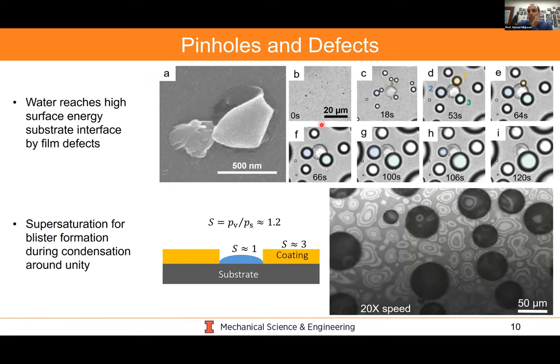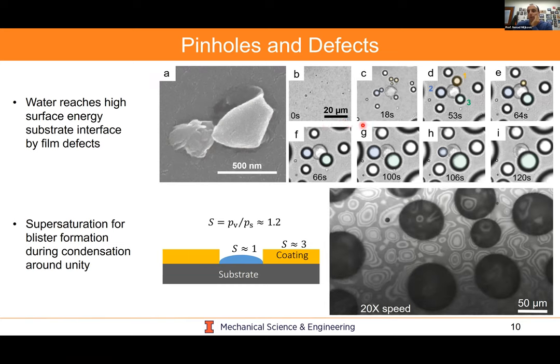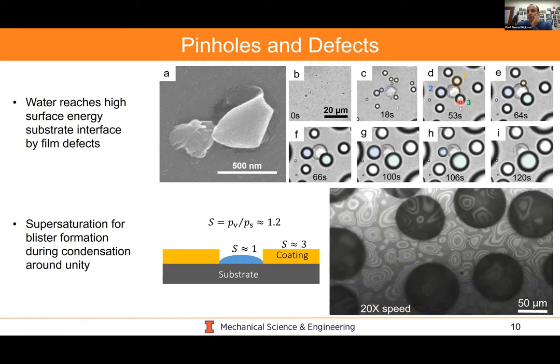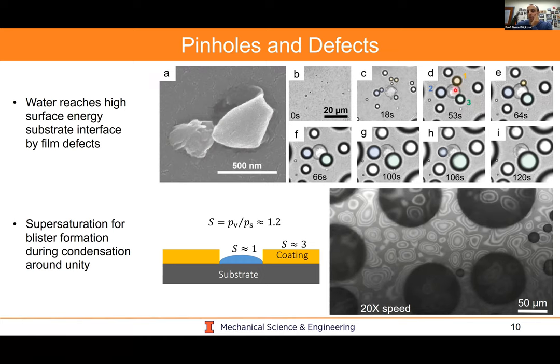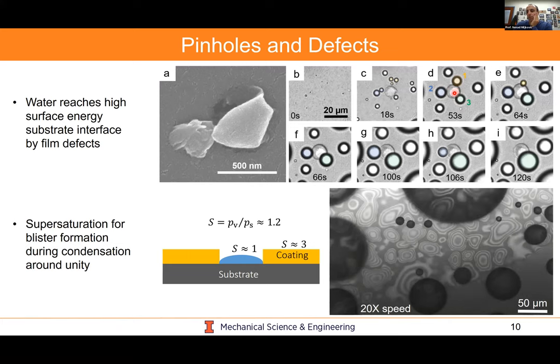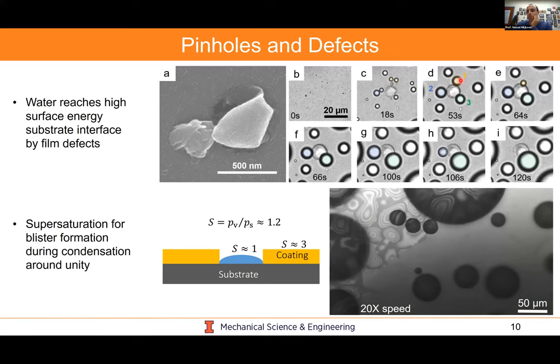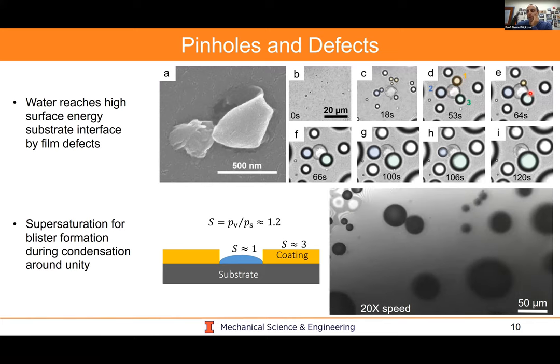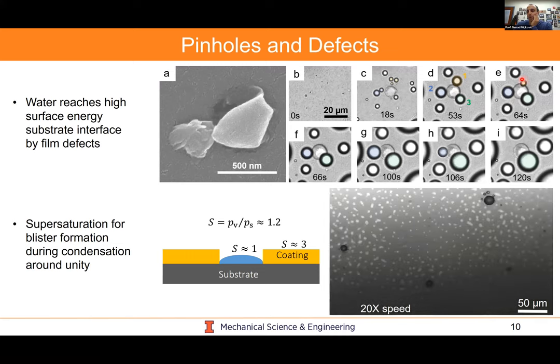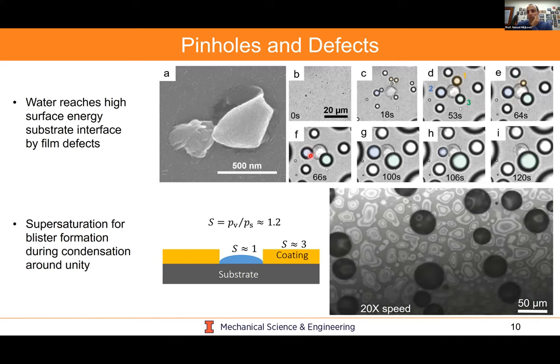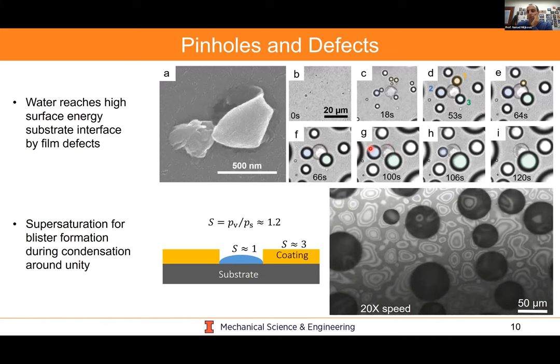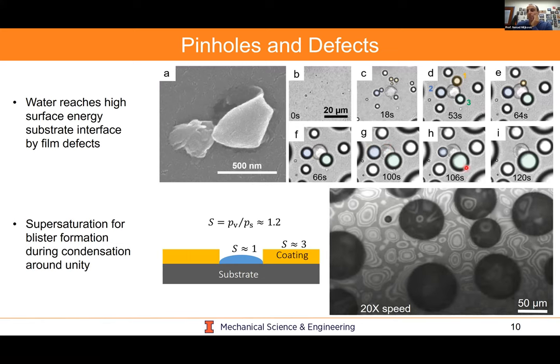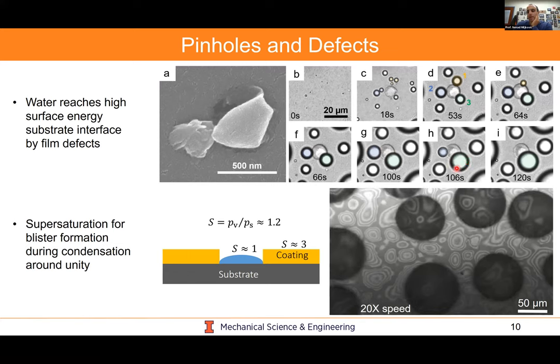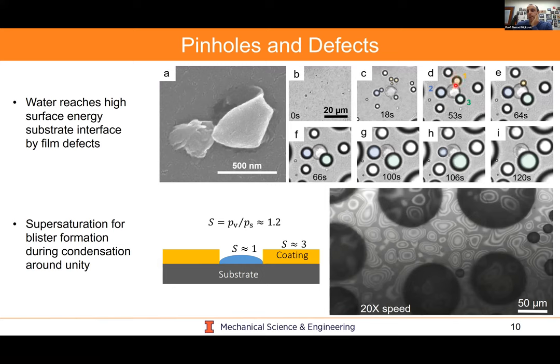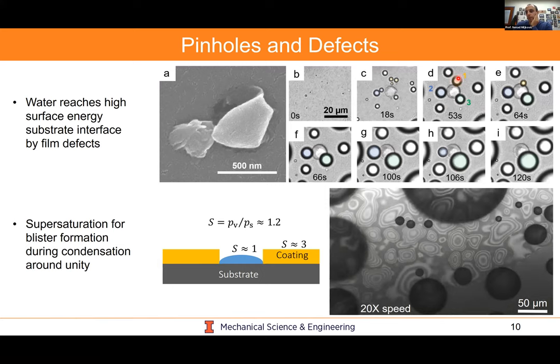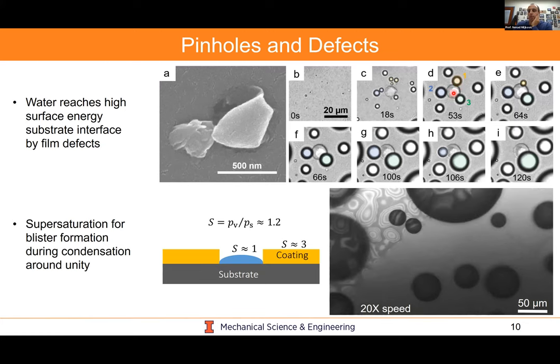Now, if we look at a time-lapse image of how condensation occurs next to a blister, interestingly, you can see droplets growing adjacent to a blister, through the blister, which was direct confirmation that these blisters are water-filled. What you're seeing here is droplets 1, 2, and 3, with a blister in between them. They grow large enough, and then droplet 1 will be injected inside the blister, and the blister will keep growing. Then droplet number 2, the blue one, will be injected back into the blister and be pumped into droplet number 3. This makes complete sense from a Laplace pressure mechanism, where droplets having high curvature will flow towards droplets having low curvature, or in this case, through the blister having low curvature into the adjacent droplet.